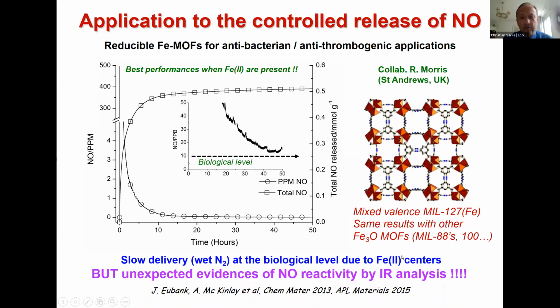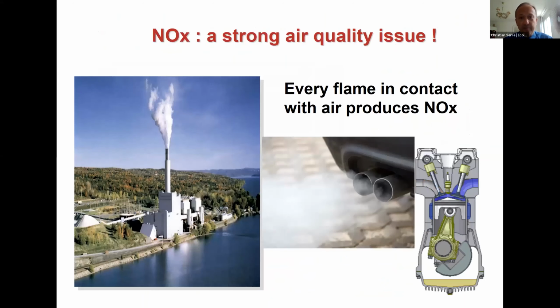But this slow delivery was also studied by infrared spectroscopy, again by my colleagues in Normandy, in Caen. What they observed, of course, was the signature of NO at the metal site, but not only. They observed other NOx species, which meant that the NO was reacting with the surface of the MOF, evidencing some beginning of DeNOx catalysis. As these colleagues were also experts in DeNOx catalysis, based on long-term experience using zeolites for car companies, they proposed that we investigate the DeNOx properties of this material.